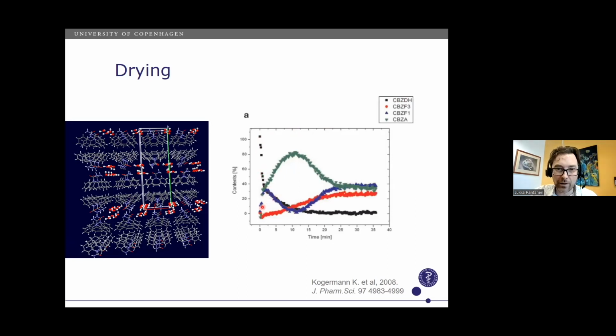Then you can see the formation of amorphous matter, which then starts recrystallizing with different kinetics into 2 different anhydrate polymorphic forms. So this is an extraordinarily annoying case, that your end product is a mixture of 3 solid forms. So this is something where you have to be very careful when you are wet granulating carbamazepine. And then this is a classical example with the effect on bioavailability.